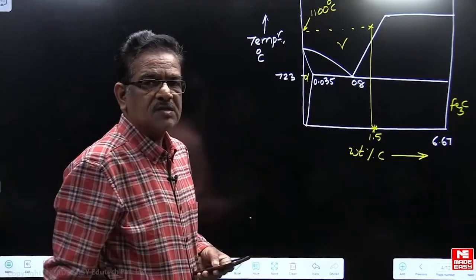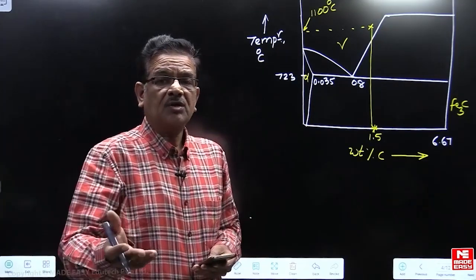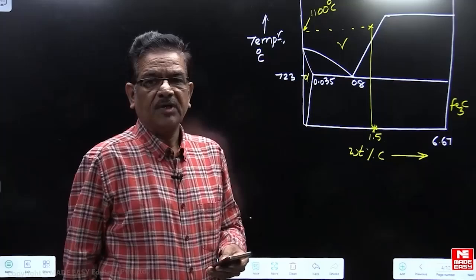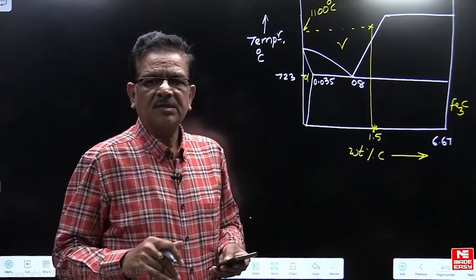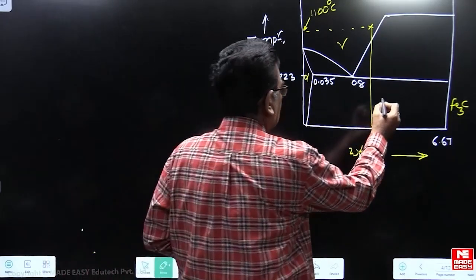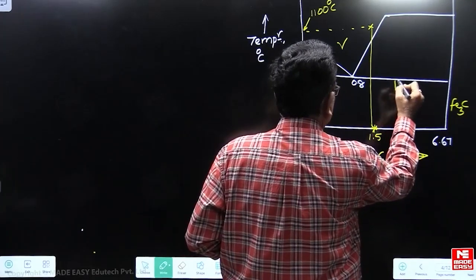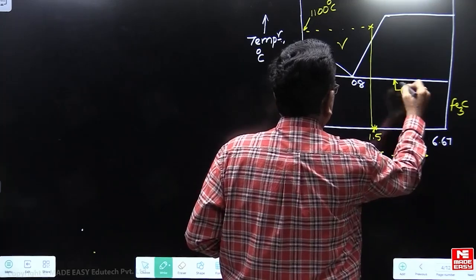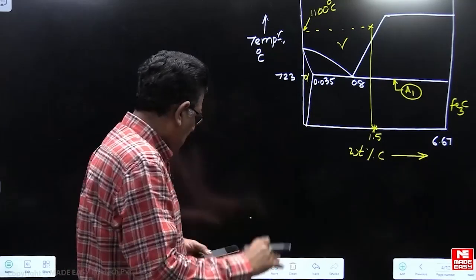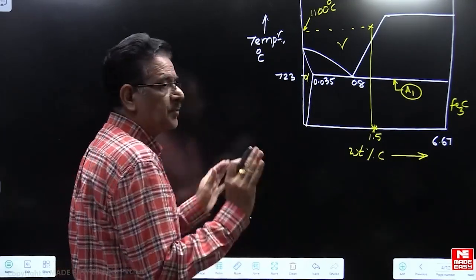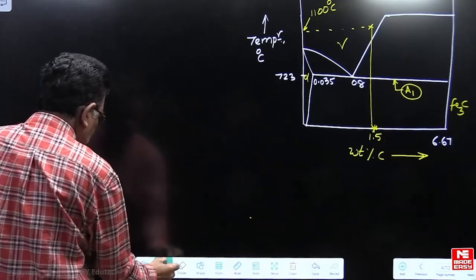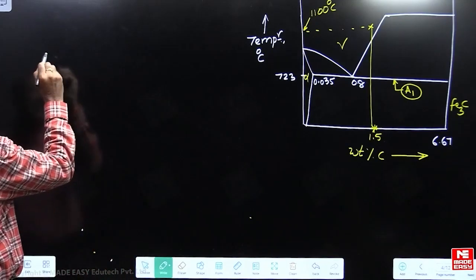The question being asked is: what is the ratio of pro-eutectoid cementite content to total cementite content? Pro-eutectoid phase evaluation must be done just above the A1 line, which is the eutectoid temperature line at 723 degrees centigrade. All pro-eutectoid phase evaluation should be done above A1 only. To evaluate this, we use the lever rule to find the amount of pro-eutectoid content.